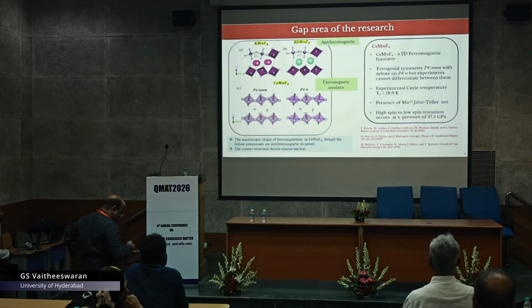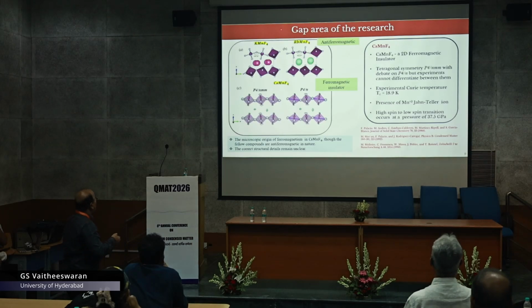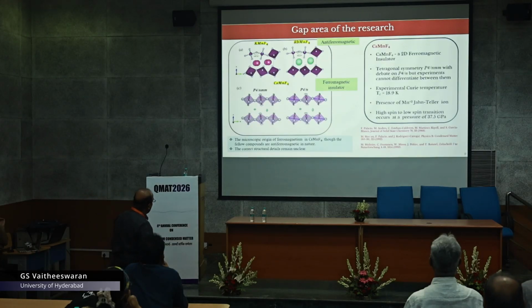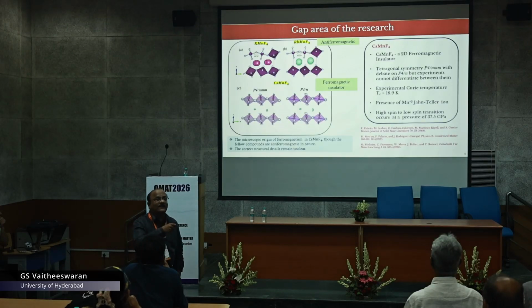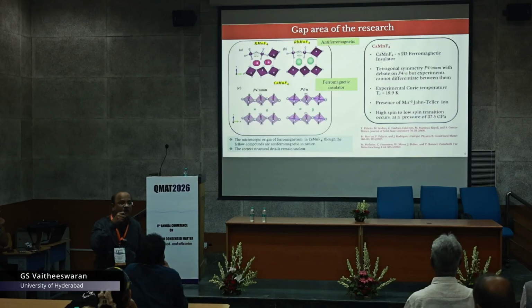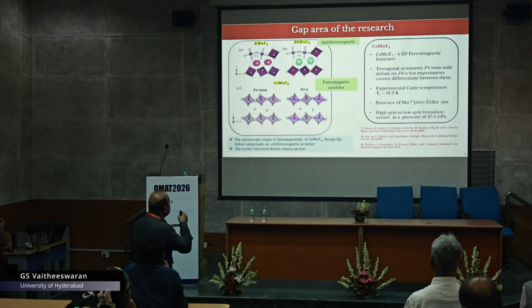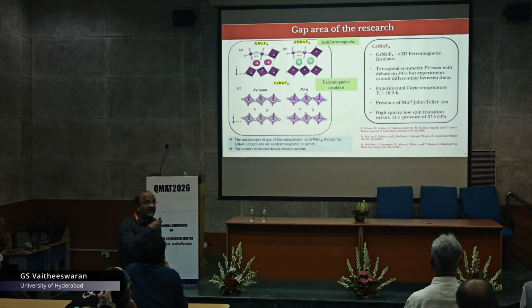So when we try to discuss potassium manganese fluoride (KMnF3) and rubidium manganese fluoride (RbMnF3), which are well known to be antiferromagnets, and then when it comes to cesium MnF4, there are two kinds of prototype space groups which are reported. Both report that the system is found to be ferromagnetic, and they still have a debate about which one is the real ground state, and if it has to be a ferromagnetic insulator, what kind of orbital ordering it should have.